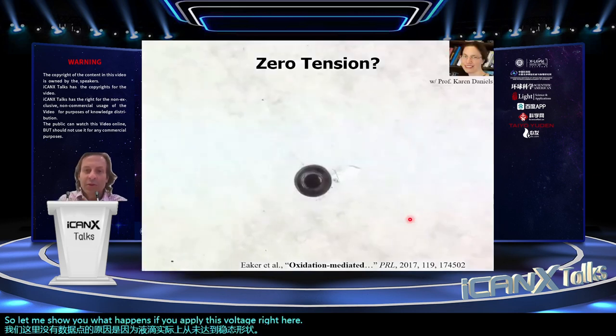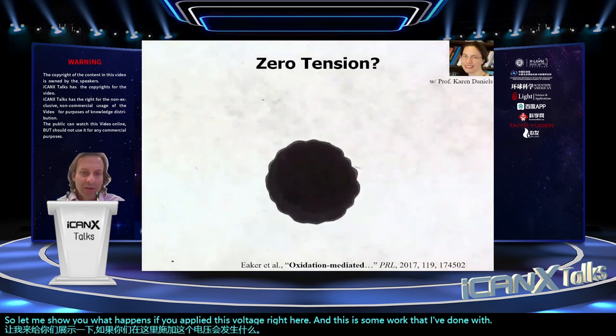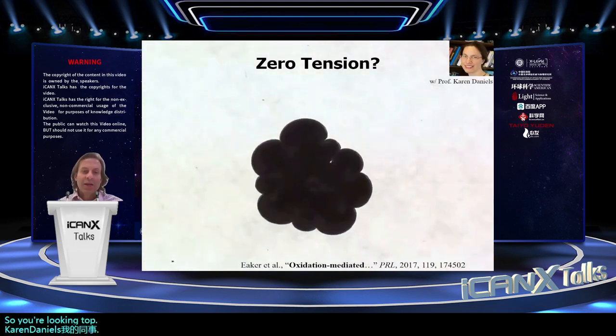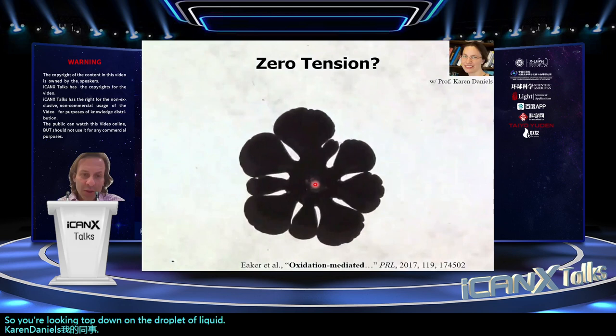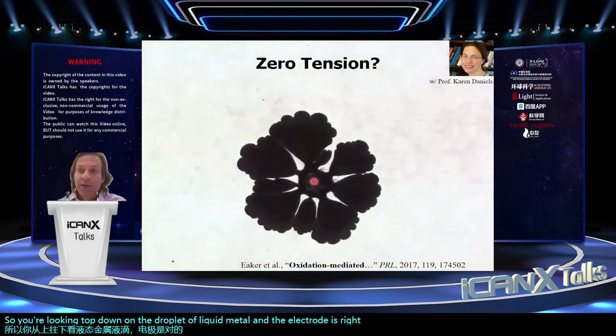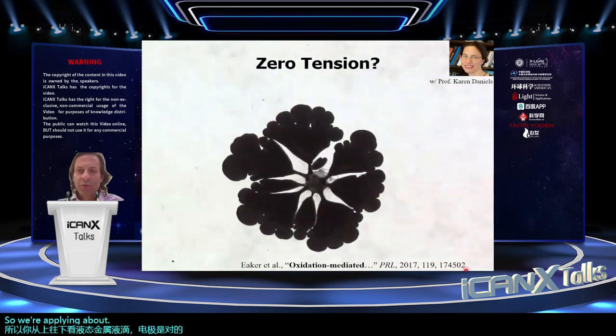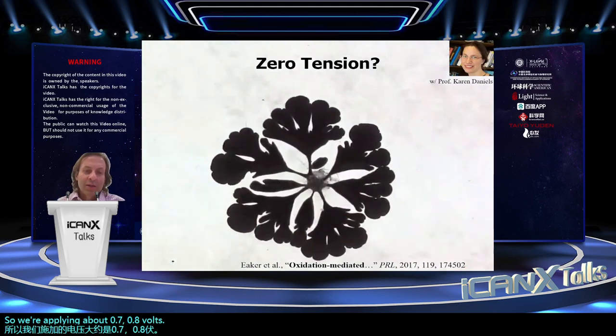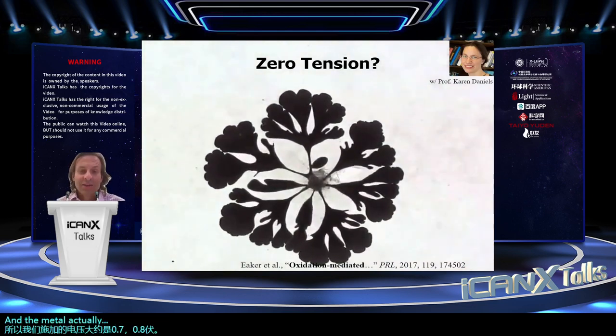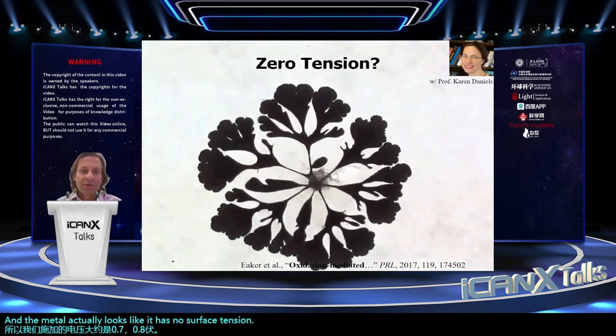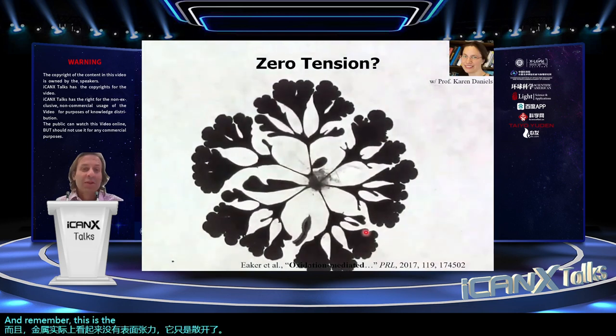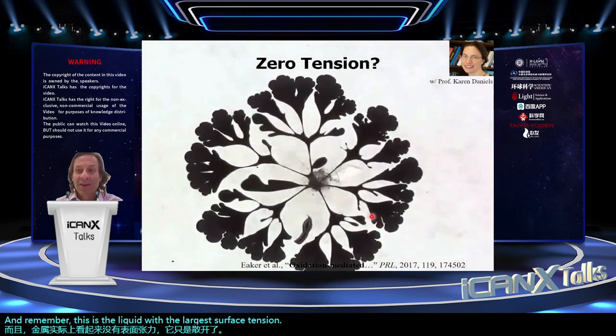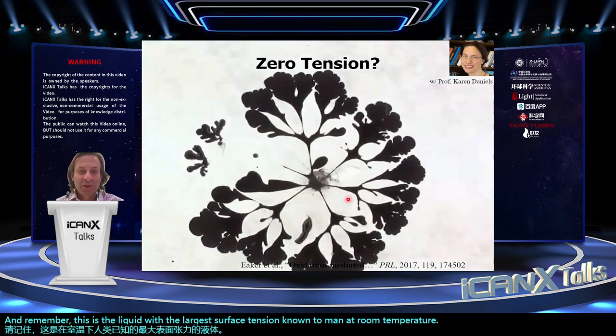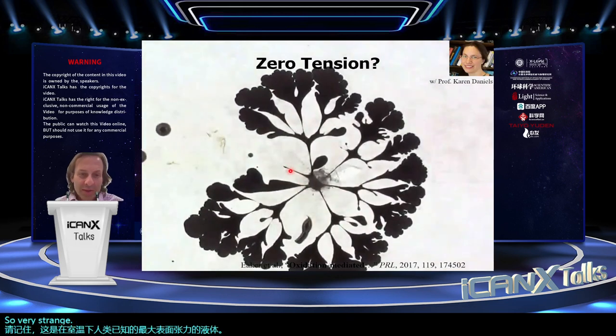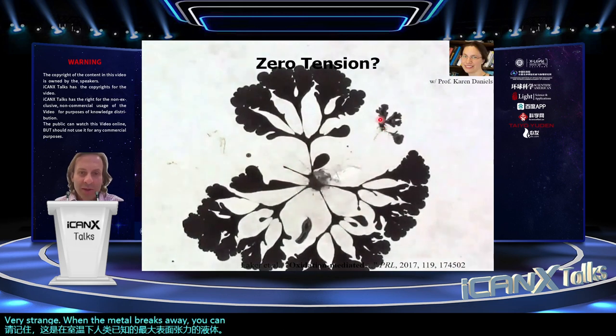And this is some work that I've done with Karen Daniels, my colleague. So you're looking top down on the droplet of liquid metal, and the electrode is right here. So we're applying about 0.7, 0.8 volts. And the metal actually looks like it has no surface tension. It just spreads out. And remember, this is the liquid with the largest surface tension known to man at room temperature. So very strange.